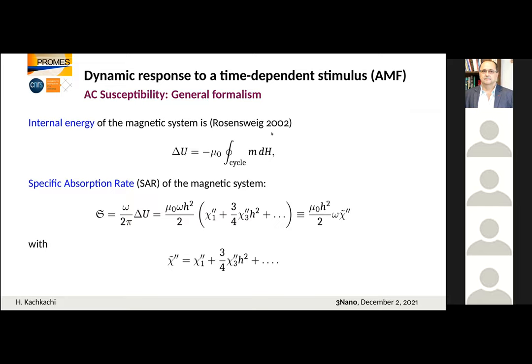And if you integrate this quantity M of T, and this is the derivative of the magnetic field with respect to time, because H is time dependent, then you can show that it is proportional to chi second, the out-of-phase component of the AC susceptibility, multiplied by the frequency and the square of the magnetic field. But this susceptibility, as we saw earlier, is an expansion. It can be written as a sum of a linear contribution, cubic contribution, fifth order contribution, etc.